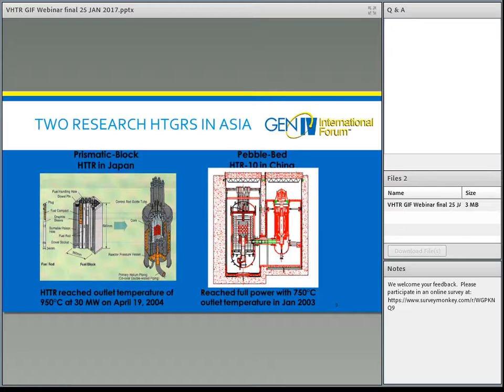So these two research reactors are still operational. Since the Fukushima Daiichi accident, Japan has not yet restarted the HTGR, but it has been ready to restart, awaiting their regulatory authority to give the go-ahead since very soon after the accident that occurred. This reactor reached a high outlet temperature of 950 degrees C at 30 megawatts in 2004, a strong achievement, and was undergoing active testing and operations up through the point when it was shut down, doing various types of thermohydraulic testing to gather data on this type of reactor.